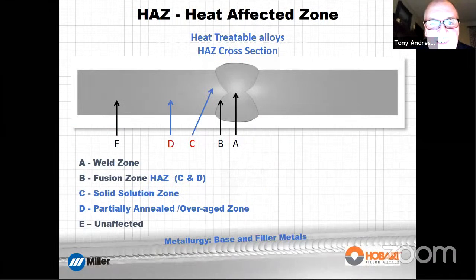Well, we really screw up the heat affected zone. This section here, well, actually D, the heat affected zone, we partially anneal it and overage it. We further precipitate the mag silicide, which weakens it, and we move it closer to its anneal strength. Now, the amount we do that is dependent on the heat input during the welding process. So this is very different than the non-heat treatables.